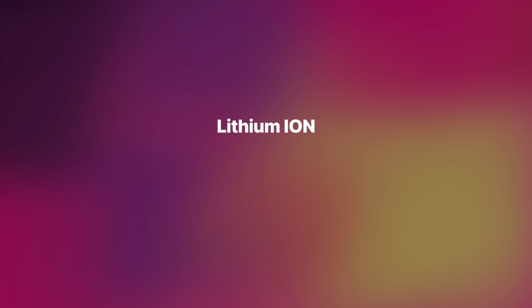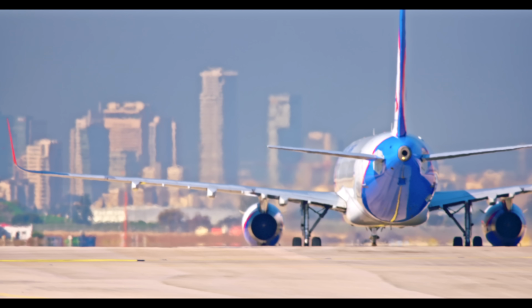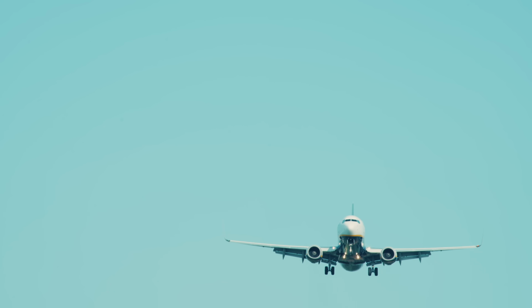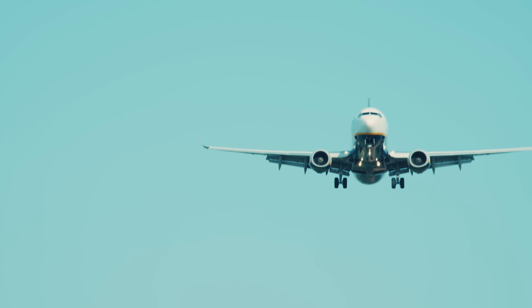Now this is crucial for airplanes. Lithium-ion batteries' optimal temperature range is between 59 and 95 degrees Fahrenheit. Such a narrow range requires active thermal management, adding weight and complexity and reducing efficiency. SABERS operating temperature can go from 32 degrees Fahrenheit, around 0 degrees Celsius, to 302 degrees Fahrenheit, 150 degrees Celsius, which means it works safely and well in pretty much all flying conditions without a bulky and energy-intensive thermal management system.